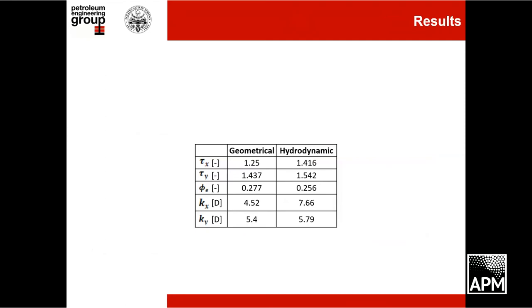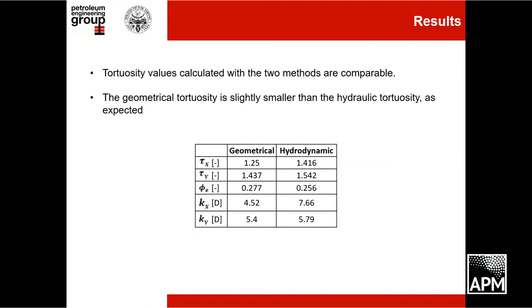The numerical results are reported in a table. Tortuosity was calculated along both flow directions, as was the permeability. The tortuosity values calculated with the two approaches are comparable. As expected, the geometrical tortuosity is lower than the hydrodynamic tortuosity. For what regards the permeability, the values of the two approaches are close.